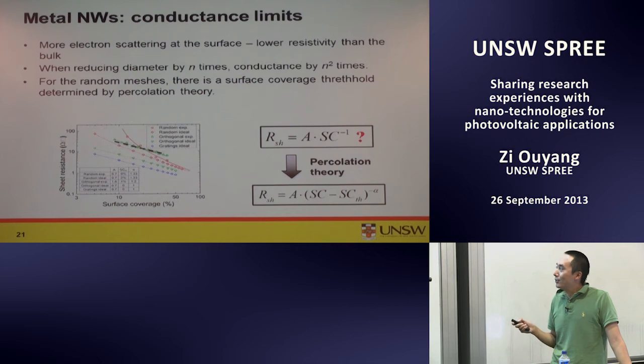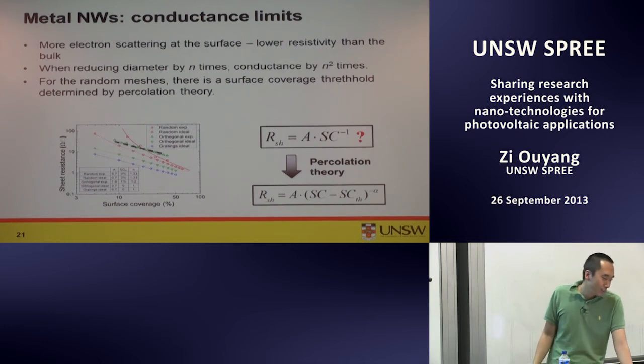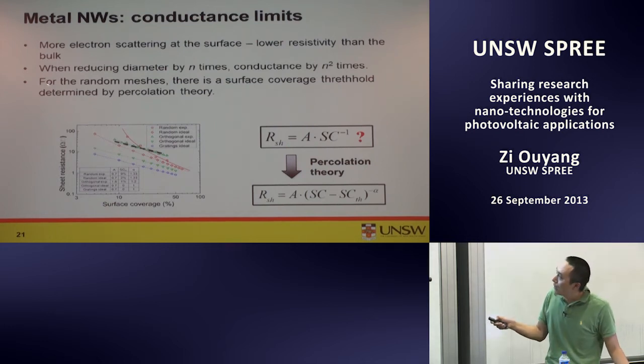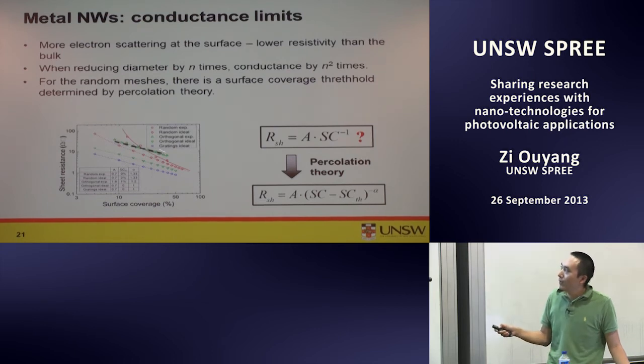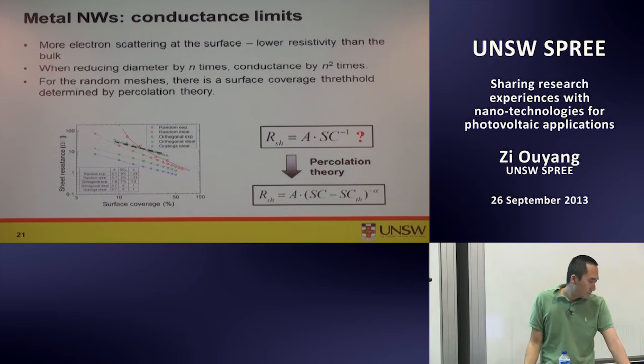So it's very interesting. We think we are the first person who really introduced this theory to these kind of applications, and we can explain our experimental result much better. So the black one used a traditional theory, which assumed the sheet resistance is actually linear to 1 over surface coverage, which is not the case.